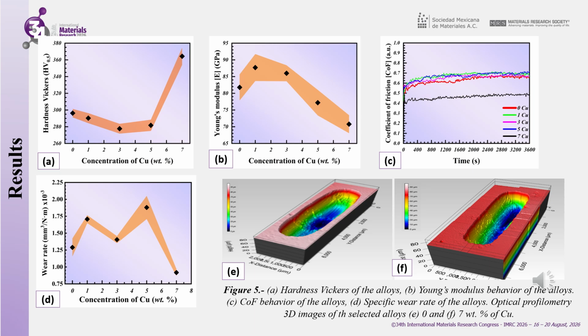Figure 5c illustrates the progression of the coefficient of friction over the course of approximately 3,600 seconds of tribological testing conducted under varying copper concentrations. It is evident from the data that all the curves show an initial increase in the coefficient of friction during the first few moments of the test, followed by a stabilization phase in which the values exhibit relatively small fluctuations. The sample devoid of copper demonstrates the lowest coefficient of friction for a significant portion of the initial test, subsequently attaining values approaching 0.60 to 0.65.